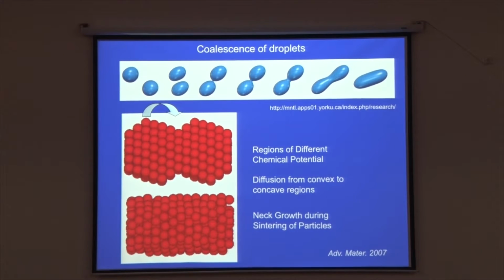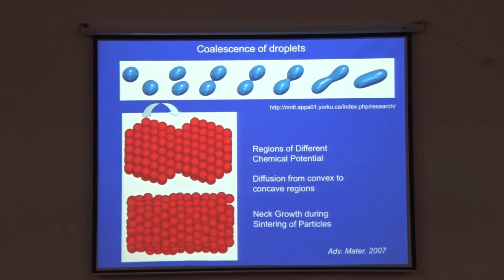If you have two such particles come and attach in this fashion, they will undergo what is called sintering at room temperature, and therefore all the 111 facets, the hexagonal facets on the sides, are now gone. We only have the two ends where the new particle can come and attach. Therefore, this dimerization process or smoothing process gives you a symmetry along this particular axis, and that is what drives the formation of the wire.